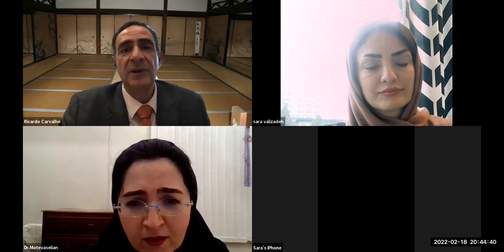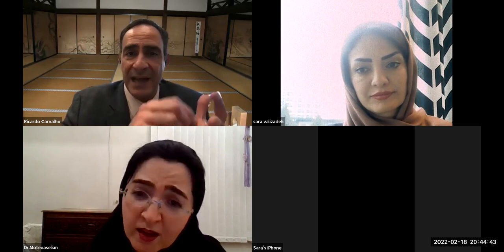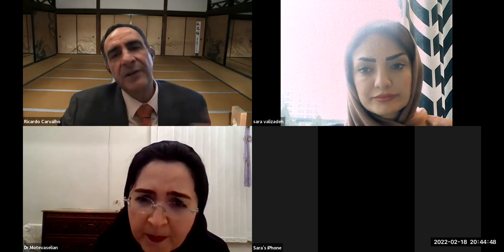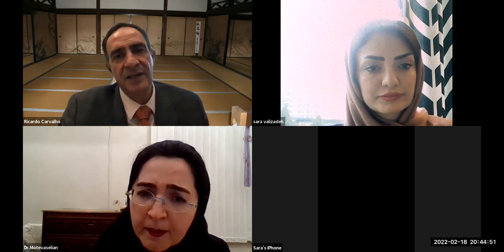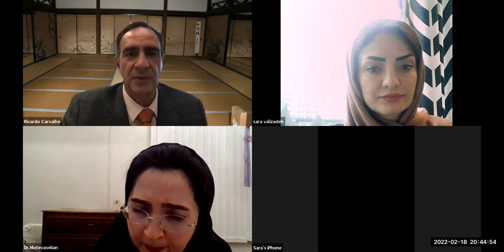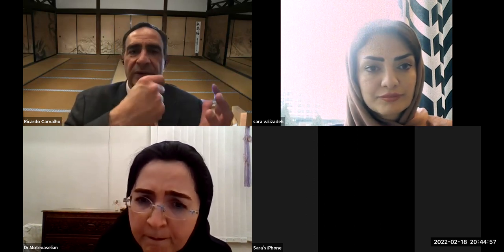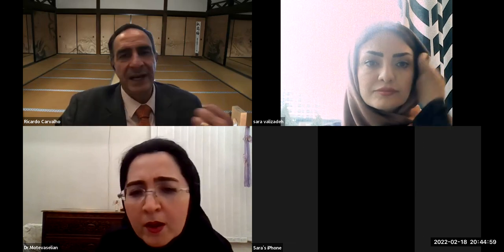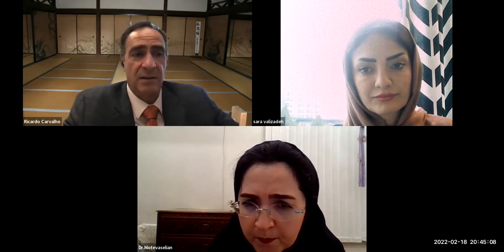No, you don't have to, but it will be hard. You will see that the acid will eventually go on the surface, the silane will eventually, and there is no problem. Once the surface is silanized, as I mentioned, it's a very strong, stable chemical reaction that you can only remove if you touch it with the burr. So the acid itself will not damage the silanized surface, and the silane layer will not damage the area as well. It will not cause over-etching or over-silanization if we do it again. Not a problem.